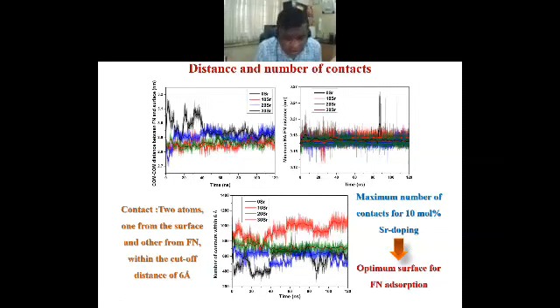And the number of contacts fluctuates over time. If you see, more number of contacts is typically achieved in the case of 10% strontium, but with more percent strontium, the number of contacts essentially reduced. And you can see this number of contacts within the first 6 angstrom, which is very critical from the surface, increased up to 1,000 and so on, which is significantly larger than all other strontium doped hydroxyapatite that you can typically see here.